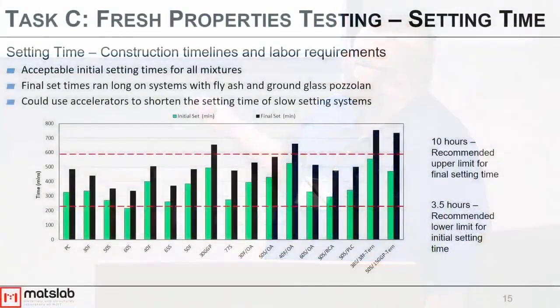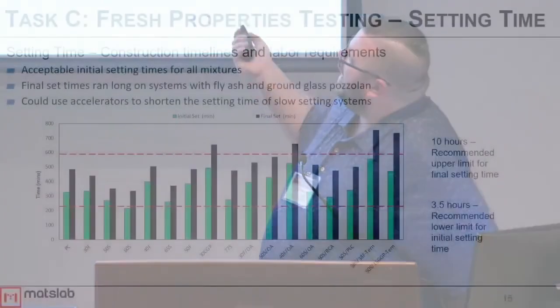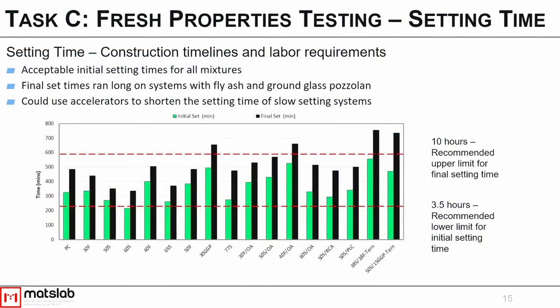This graph shows the initial setting time in green and final setting time in black of the different concrete mixtures. We set upper and lower quality limits, so that's what these red lines are. So for setting time, our lower quality limit was a 3.5 hour initial setting time. So we wanted at least 3.5 hours for initial working time before you got to that initial set where you really couldn't do your finishing procedures well anymore. And then we didn't want our final set to happen any longer than 10 hours, right? Preferably lower than that, but this was the max level that we were willing to accept for certain mixtures.